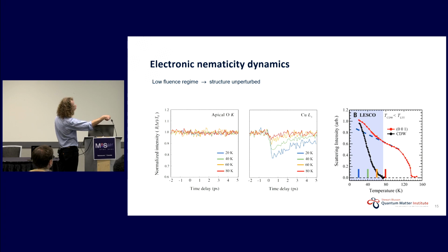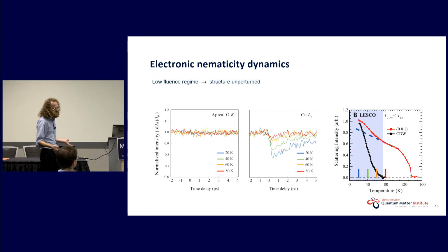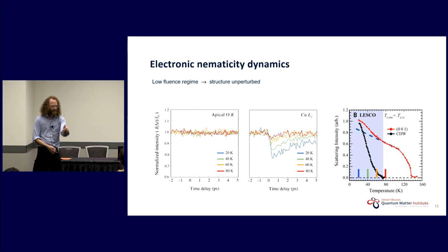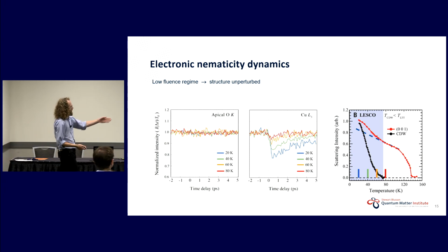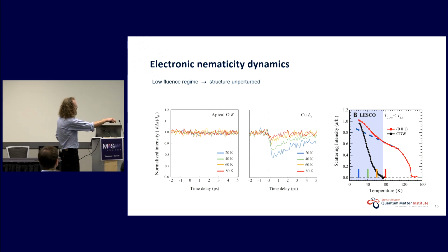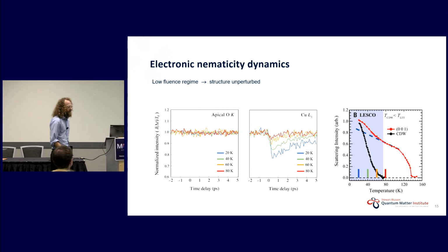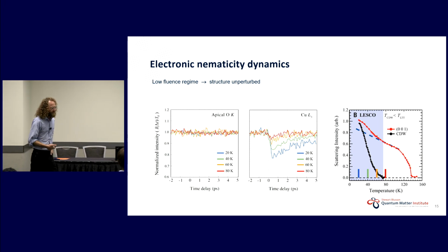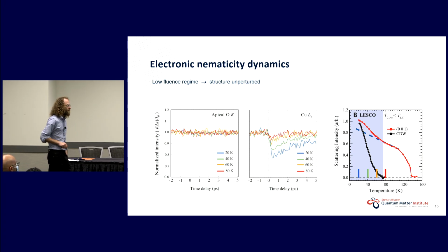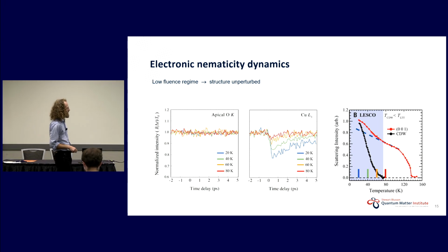This is the laser on divided by the laser off, okay? As a function of temperature. You go to the copper L3 edge, and you get this temperature-dependent, fast response that looks exactly like the CDW dynamics in LBCO, measured by Matteo Mitrano and others. And here you can see the temperature. It goes exactly with the CDW. So we're kind of just measuring the CDW, but we're measuring the rotational symmetry breaking in that state directly, okay?